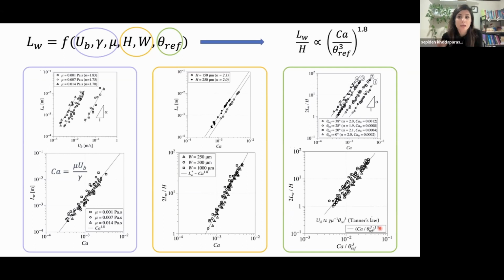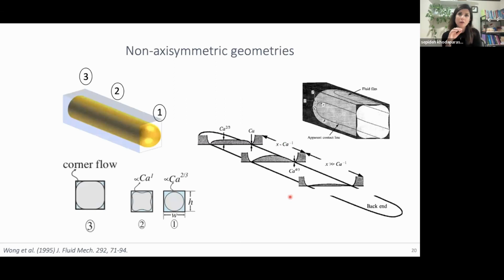And so we end up with this particular prediction method, where the wetted length in front of the bubble is only predictable with the capillary number. It's basically the drainage of the fluid towards these corners and the van der Waals interactions that cause this drainage. And if we compare our data with the theoretical data in the field, we know that the dry out typically occurs in this region. So you never get to this for the range of capillary numbers that we studied. The dry out is typically happening in these regions and always starts with this minimum film thickness.